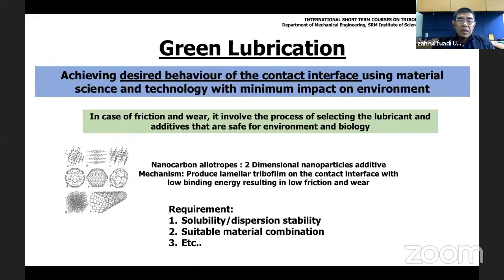But what about the shoes? Are you going to reduce the friction of your shoes? I don't think so. What about your car tire? Do you want to reduce the friction of your car tire with the road? I don't think so. But in the case of friction and wear, if you want to reduce it, it will involve the process of selecting the lubricants and additives that are safe for environment and biology. And this can be achieved by using nanocarbon allotropes, which are two-dimensional nanoparticle additives. The mechanism is that the two-dimensional nanoparticles will be delivered to the contact interface during the friction, and will produce lamellar tribofilms on the contact surface with low binding energy, which results in low friction and wear.